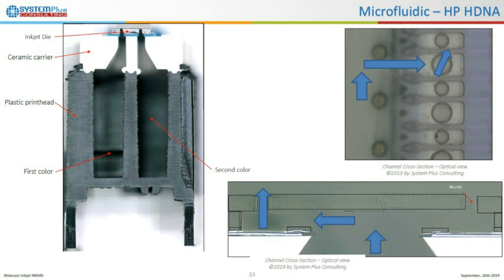Here is the nozzle. You can see there are 2 different nozzle sizes, because this printhead has the new technology of HP, the dual drop weight, that allows different sizes of drop, between I think 2 or 3 picoliter and 10 picoliter per drop, and you can select if you want a little drop or a big drop. It's the first time that a thermal inkjet die can have dual drop weight.